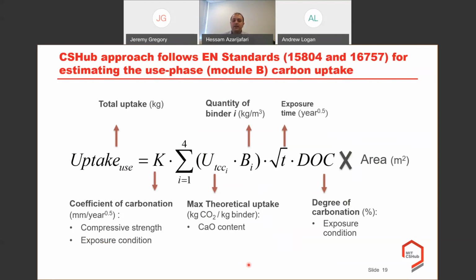On the other side, we have the maximum theoretical uptake, the maximum amount of kilogram CO2 that can be absorbed by kilogram binder. Remember, the binder can be limestone, it can be slag, fly ash, or Portland cement, which is multiplied by the quantity of binder that we have here. And again, the exposure time, the square root of exposure time, and the degree of carbonation. Again, this degree of carbonation will help us adjust and include the exposure condition of the concrete.